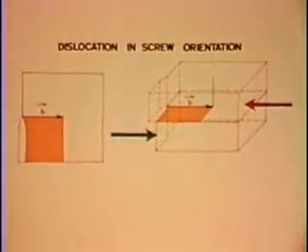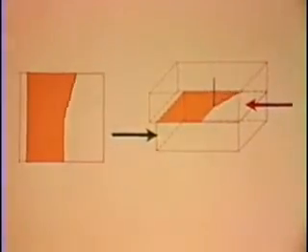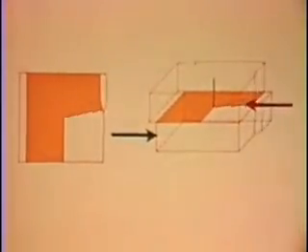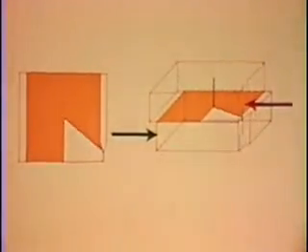Repeated rotation of the dislocation has the same effect as a series of dislocations sweeping over the slipped plane. Rotation about a point is therefore known as a single-ended source for generation of dislocations.